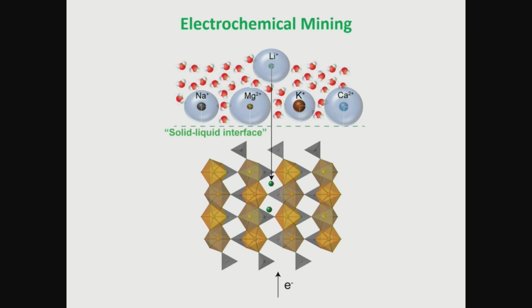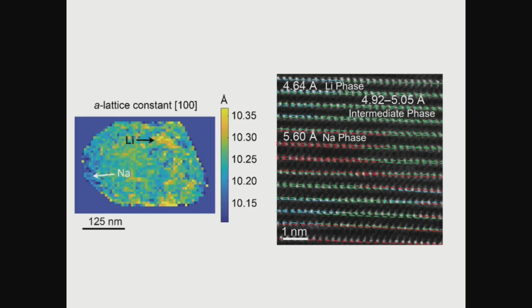And how can we deal with that? So we turn to advanced characterization tools. We want to have a deep understanding of how this lithium and sodium are competing in the same host inorganic materials. If you look at all these pictures, we have the atomic resolution views of the atoms. And the lithium and sodium, they don't like each other a lot because they still have a big diameter difference. So what they tend to do is separate apart in these materials.